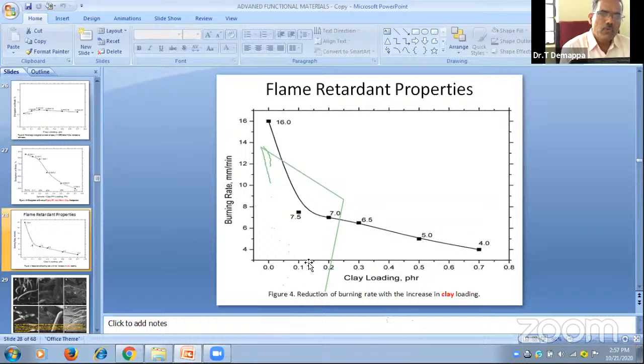Where we add just 0.1 phr of clay, you see that we cannot burn this length of sample, not 16 millimeter. Only able to burn 7.5 millimeter per minute. For 0.2 phr, 7, 6.5 for 0.3 phr, up to 4. You can imagine that 16 to 4. Okay, that means this is a very, very important parameter for fire retardant material, just by adding clay.